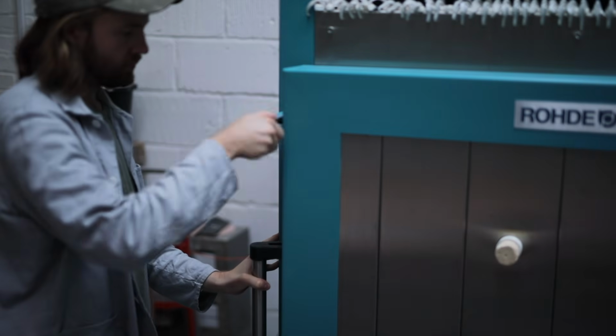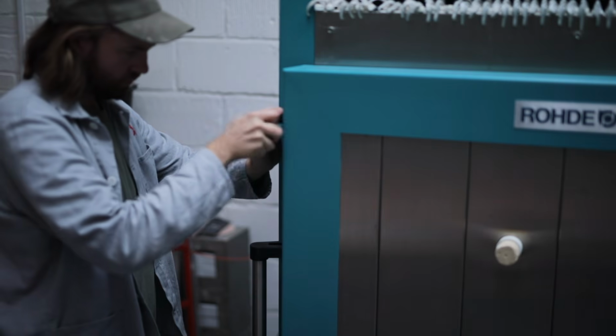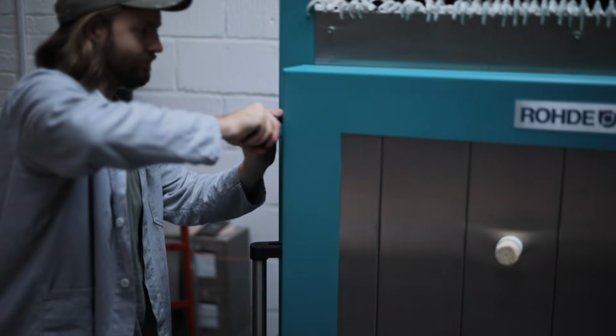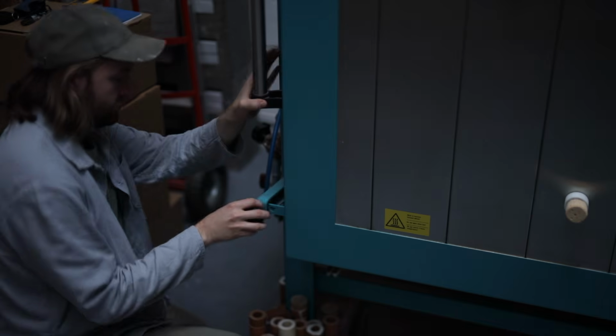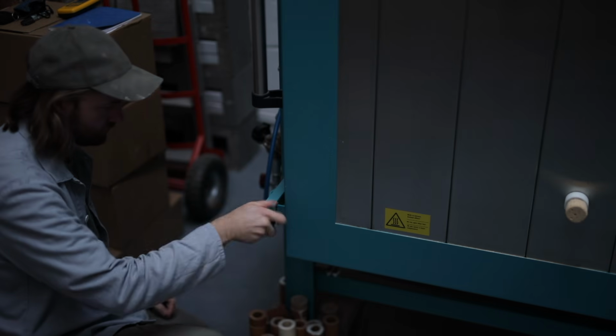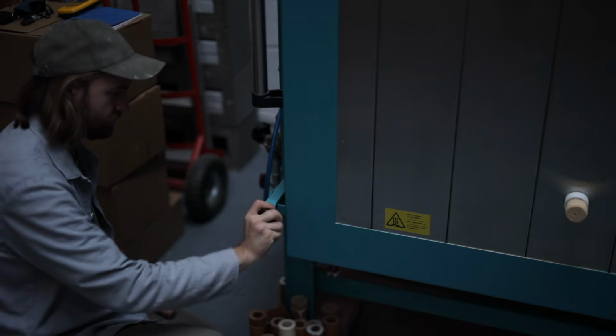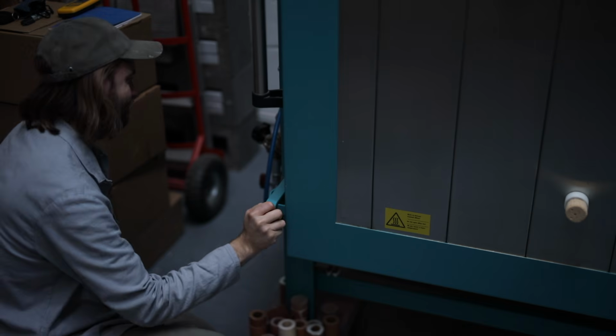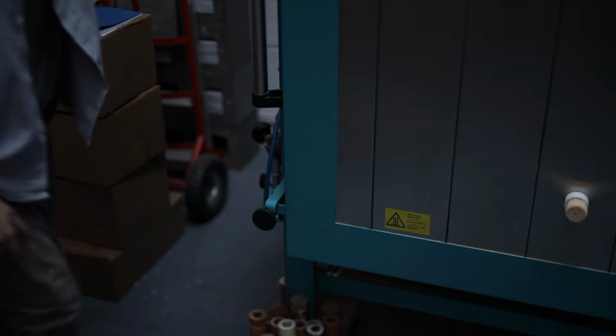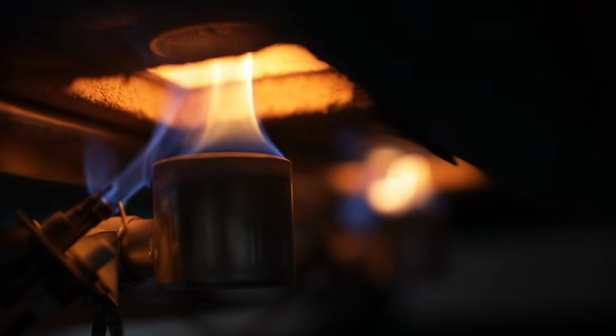These reduction firings take about 9 hours from start to finish, culminating in a temperature of 1290 degrees Celsius or 2354 Fahrenheit. Every input for firing this kiln is entirely manual, from the gas pressure, the air pressure, and the damper position. But essentially, all I'm doing is slowly firing the kiln up at the beginning, so everything inside is really thoroughly dried out. And as time progresses, I gradually increase the temperature. I check the kiln every 30 minutes and do any adjustments that need to be done in order to keep the kiln's firing schedule on course.